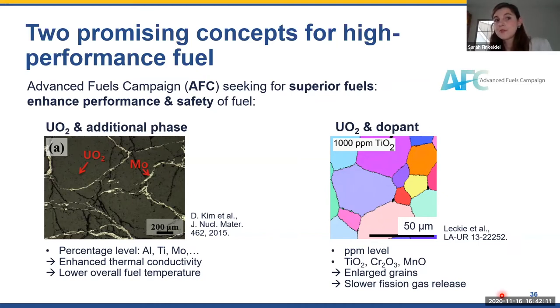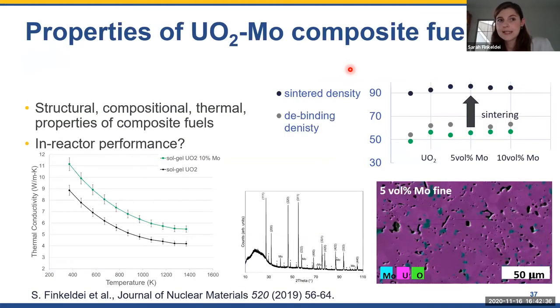And there are two different areas for high performance fuels that I would like to talk briefly about. One is adding an additional phase to uranium dioxide, and the rationale behind it is to increase the thermal conductivity, which is one of the main drawbacks of uranium dioxide. And the other method is to add a dopant to the material to increase the grain size to potentially slow down fission gas release.